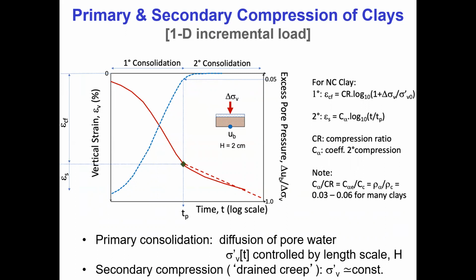We measure, of course, the strain, and we measure it against time. I happen to plot time on a log scale because the figure is most familiar on the log scale. You will see that in red, I've got the strain, and on the other axis, I've got the water pressure at the base, which is essentially the center of a two-way draining sample. And you'll see that the water pressure initially is very high, it can be almost the same as the total stress we apply. And with time, the water pressure dissipates, we end up with no water pressure in the system. Everything, total stress, is converted to effective stress.